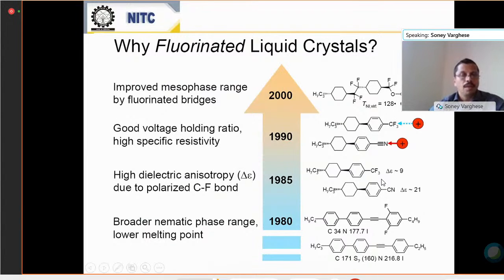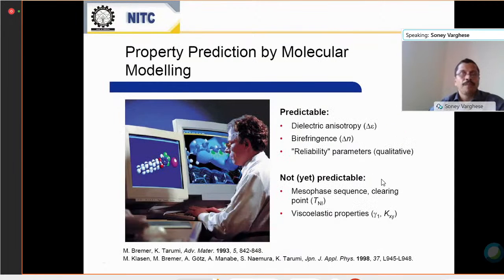And you can see broader nematic phase range, lower melting point. So because of these reasons, we are basically looking for fluorinated liquid crystals, right? So people do synthesize molecules using some molecular modeling methods, right? So you can predict many of the parameters of the molecules like dielectric anisotropy, birefringence, then other viscosity or viscoelastic properties, which are very, very important for a successful liquid crystal molecule, right?